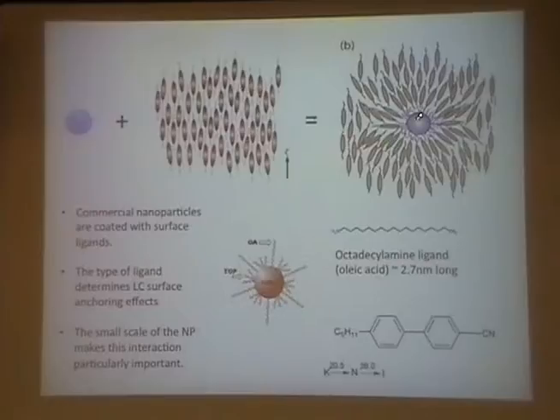Okay. Let's say we've got some oleic acid on the surface, this kind of molecule. Well, when you look at the interaction between these two carbon chains, the one from the molecule and the one from the nanoparticle, we can pretty clearly see that this liquid crystal is not going to want to lie parallel with the particle, and you're going to get some kind of preferred orientation. So you can see the molecules lining up around the outside of the particle, creating a defect, like this hedgehog defect. The type of ligand on the surface of the particle is going to determine the anchoring effect of the liquid crystal. So that's going to be very important. In the case of a particle with oleic acid in 5CB, we're going to get something like this happening.